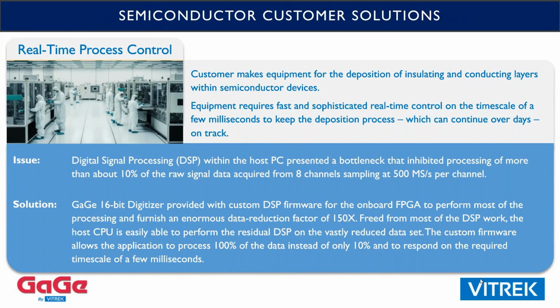And by doing that, that reduced the processing load on the host CPU. It had to deal with 150 times less data, and the burden of this pre-processing step was alleviated. So by doing that, they were able to go from consuming and processing only 10% of the data to consuming 100% of the data, and that was able to work in their control loop.